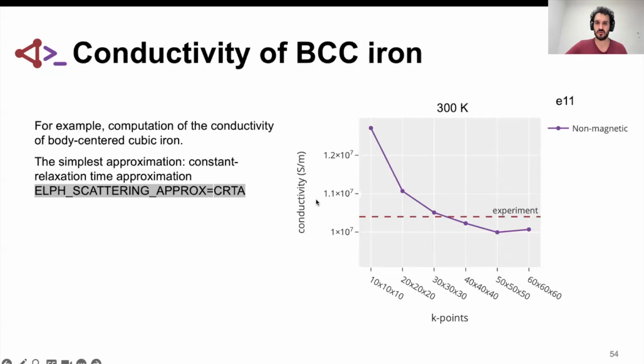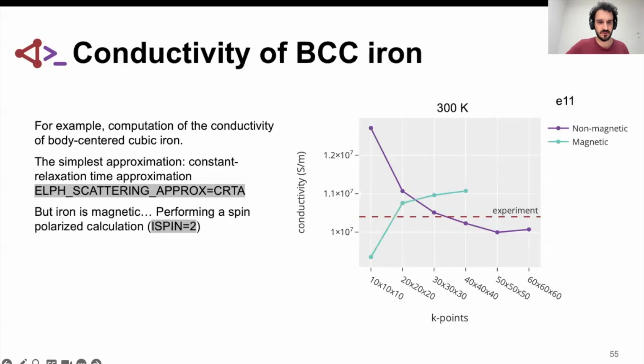Here I show a plot of the conductivity as a function of the K-point sampling. The red line is the experimental value. You can see that we are just slightly underestimating experiment. But this constant relaxation time, of course, is a parameter that we put in the INCAR file. So we can just change it and we would get the value on top of experiment. So that's not meaningful by itself.